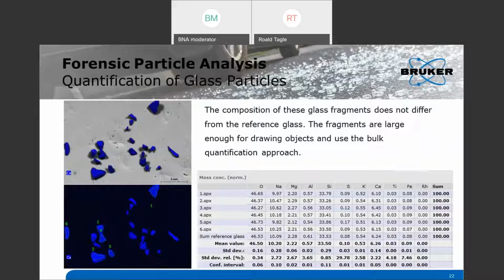So the main advantage, and that's something that I'd like to emphasize, of using a scanning device is that you have the possibility to identify the representative areas of samples that might not be homogeneous. Just doing a point analysis starts from the precondition that this point is representative for the other part of the sample that I'm not measuring, and this is also always only an assumption.